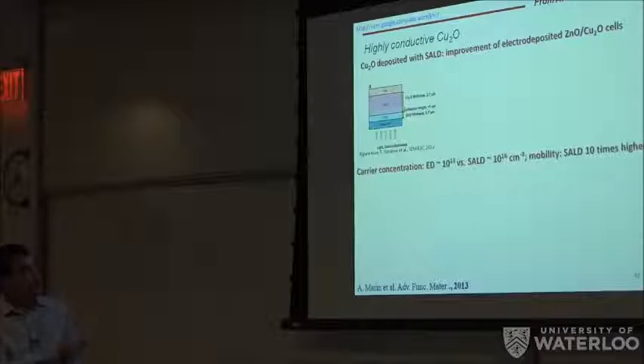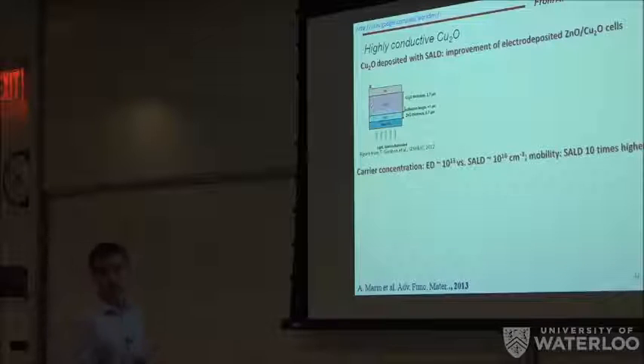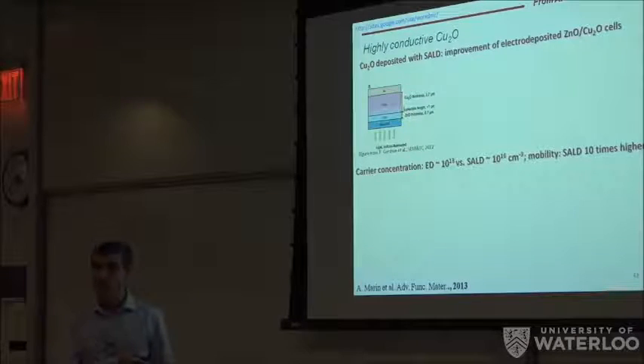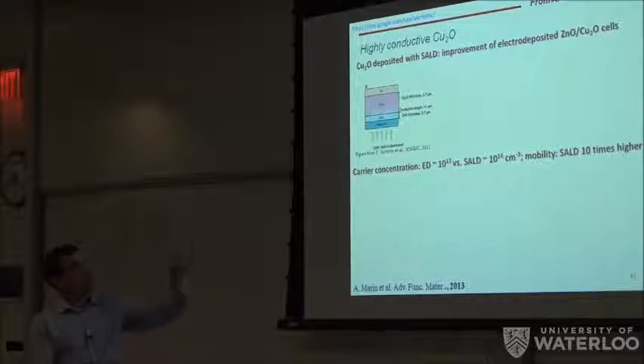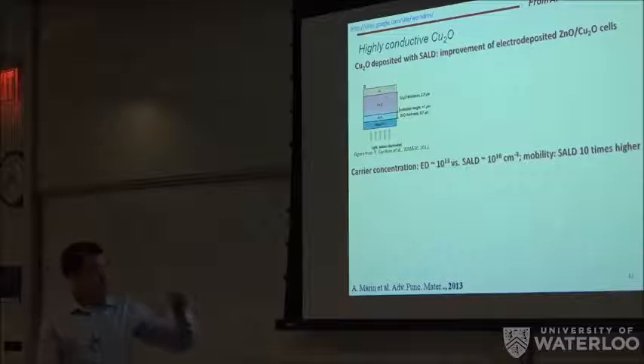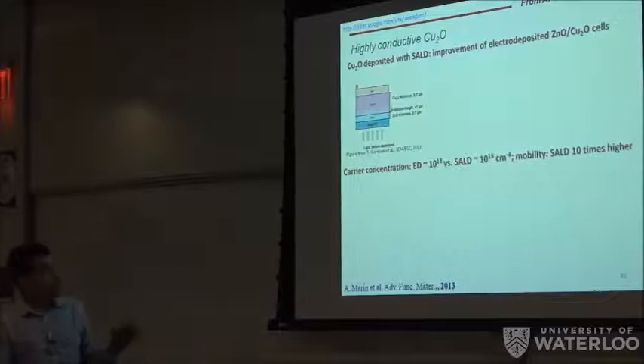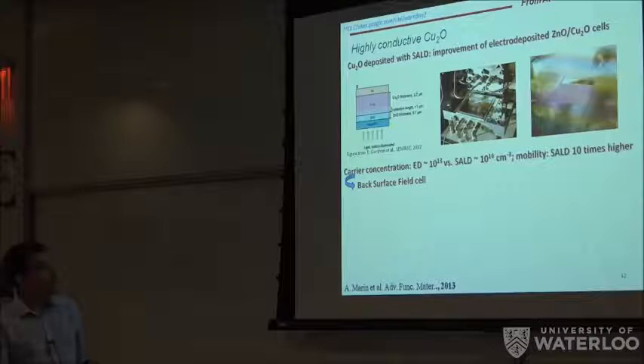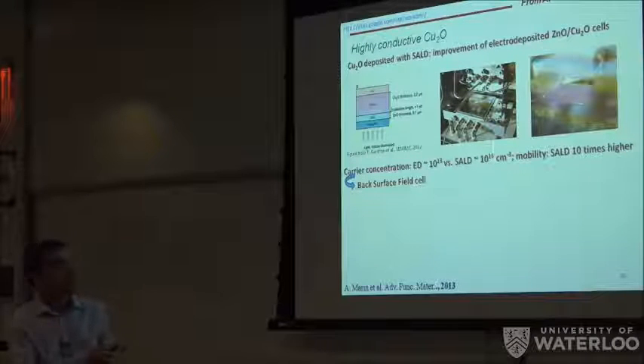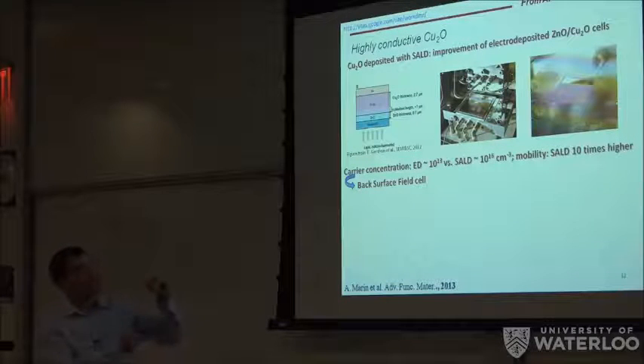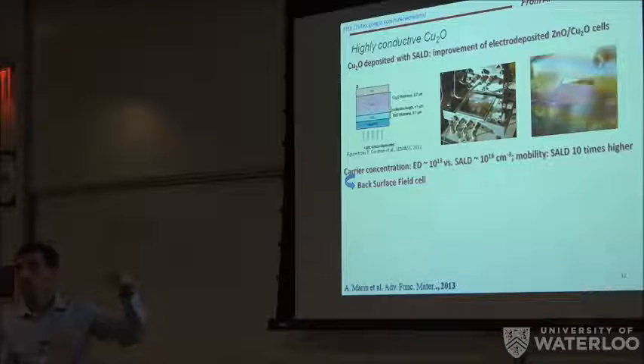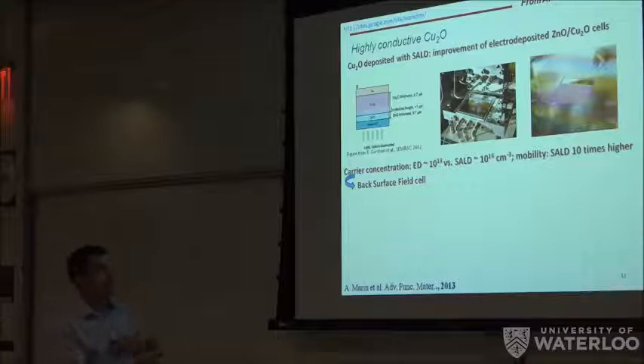And we tried to take advantage of this value because the electrodeposited copper oxide that Kevin and other members of the group were using had a carrier concentration of 10 to the 13. So what we did, we tried to fabricate a more complex cell in which we deposited a layer of cuprous oxide by SALD on top of the previously electrodeposited copper oxide, in what is called a back surface field cell.